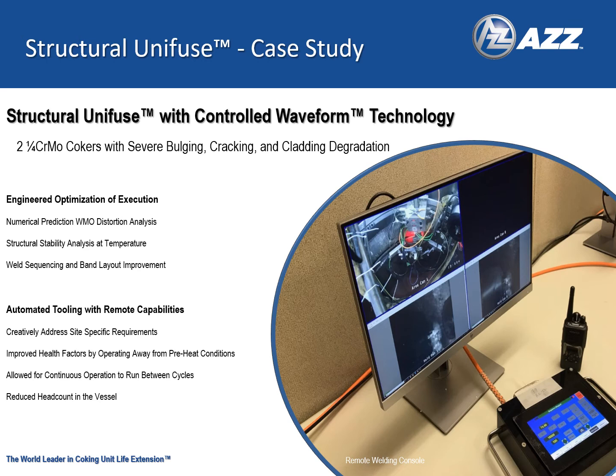AZZ was able to model vessel structure and loading conditions and apply heat input models to simulate the welding of an overlay with multiple machines in the area of concern. We were able to demonstrate that the vessel would safely support a significant number of welding arcs in parallel, and that would easily exceed any practical applications in a scope of this size. Using the distortion model, we were also able to provide the customer with weld sequencing plans and significantly improve the